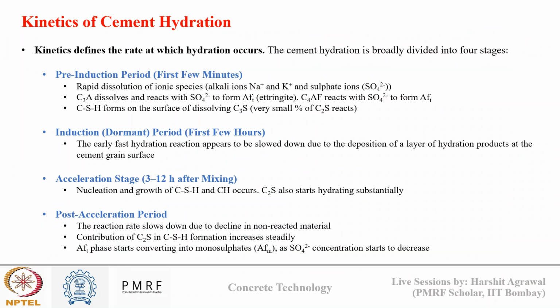Okay, so when we talk about hydration kinetics, it involves four stages. There is the pre-induction period, that is the first few minutes, where there is rapid dissolution of ionic species like sodium, potassium, and sulfates. C3A starts to dissolve and react with gypsum to form ettringite, and there is a little bit of CSH formation that also happens on the grains of C3S. So this is the pre-induction period.